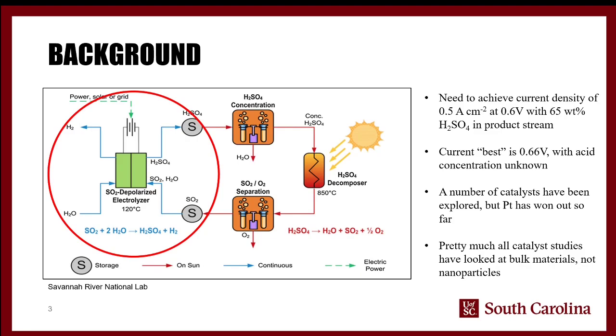The current best achievement in terms of the cell voltage is 0.66 volts. And that was done here at the University of South Carolina. But the acid concentration at that potential is not known. And so it's a step in the right direction. The voltage has steadily come down from, starting at around 1 volt to about 0.9, 0.8, 0.7, and it's now been pushed down to about 0.66.